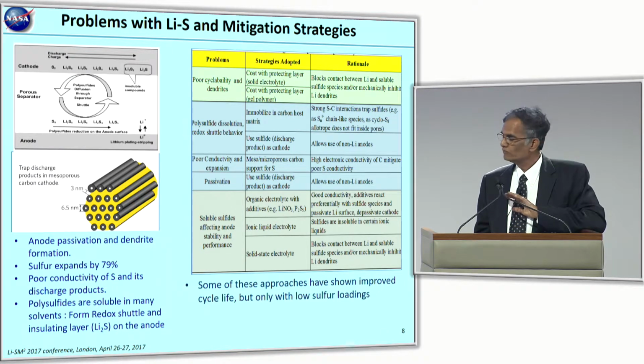So we have seen some interesting data. A lot of discussion has been going on in this conference as well. But in general, all the data that we have seen pertains to low loadings in the range of, say, 2 to 3 milligrams per square centimeter. I've seen some numbers here close to 5 milligrams per square centimeter, but our belief is that's not adequate to meet the energy density that we need, 400 watt-hours per kilogram.